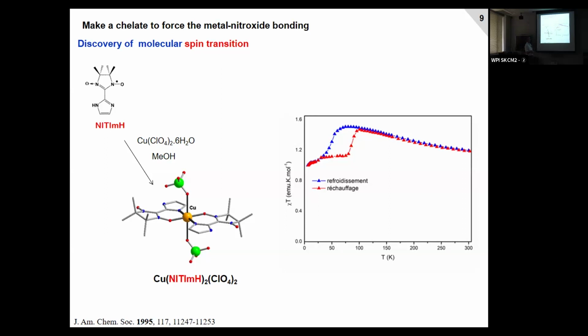At the end of January, I measured the compound on the SQUID magnetometer, the one you have. At the beginning, I thought it was a problem with oxygen, but when you measure magnetic properties, you always have to take care when you cool or when you heat. Sometimes it's not the same thing. Here I measured this compound from room temperature to room temperature and discovered this effect. So it's completely reproducible.